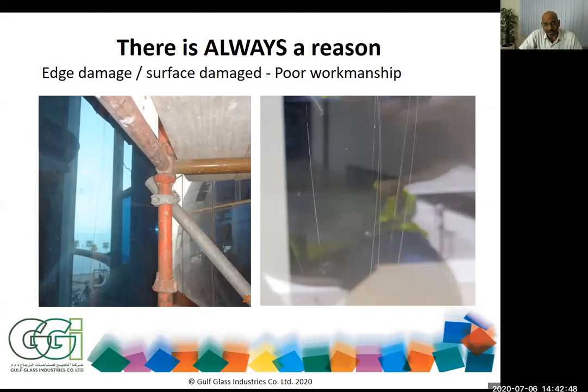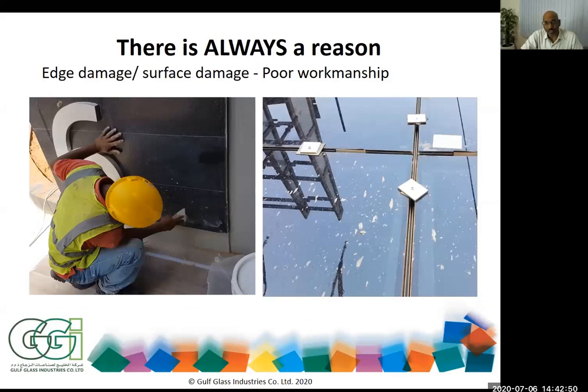This is the way that we see things on the site. These are some of the examples where we have seen people using metallic scrapers to clean glasses. The other concern that we have experienced is concrete slurry and construction materials that fall on the glass surface. And the glass has not been protected. And this creates surface damage.